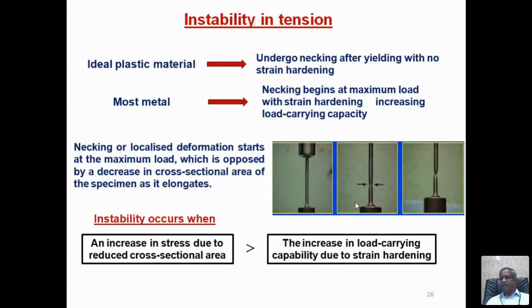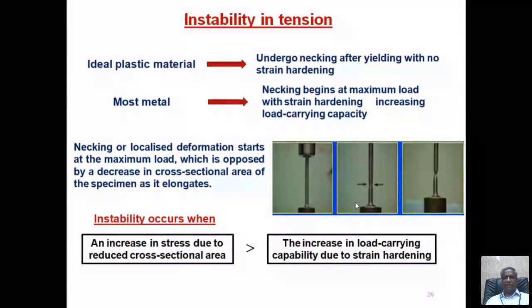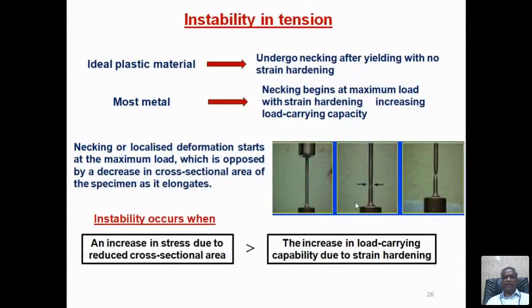Most of the metals, necking begins at maximum load with strain hardening increasing load carrying capacity. So most of the common metals, because the ideal plastic material we are not using. Most of the metals we are using will start the necking. Necking means, as I told, some instability will occur. Okay, so this is necking or localized deformation, which starts at maximum load and is opposed by the decrease in cross-sectional area of the specimen as it elongates.